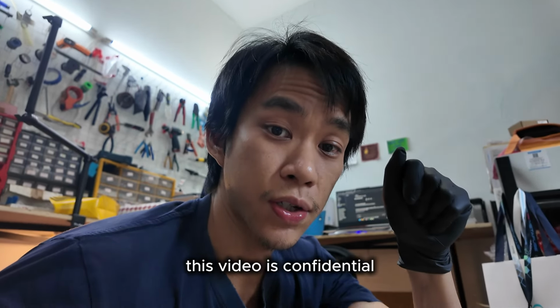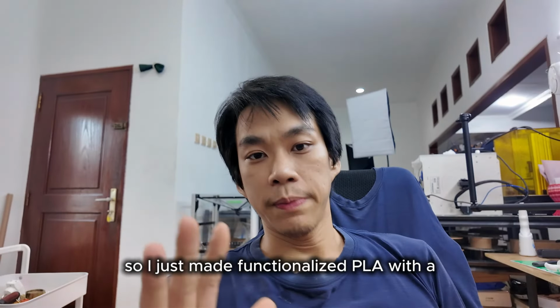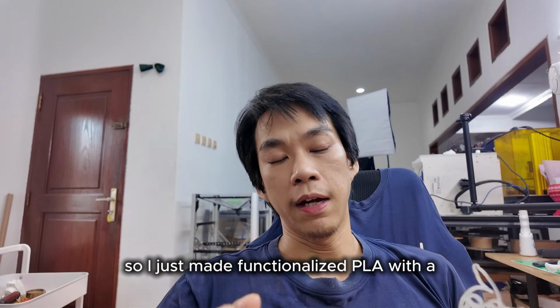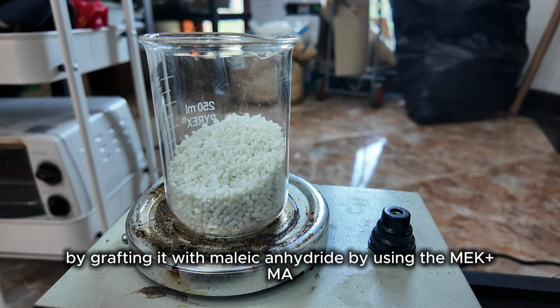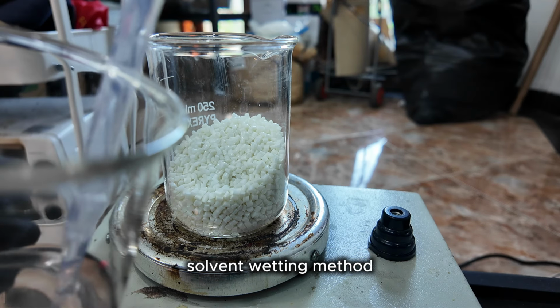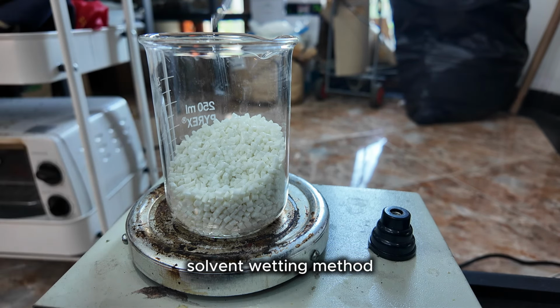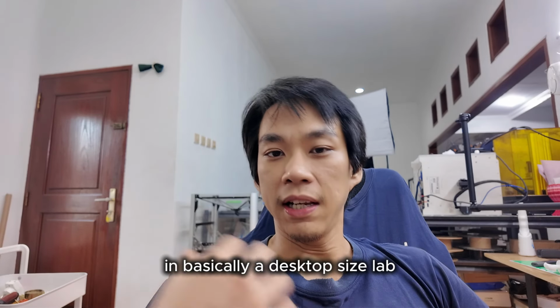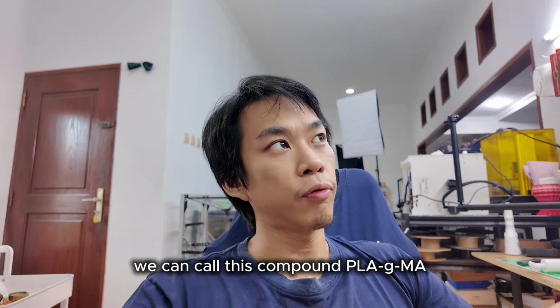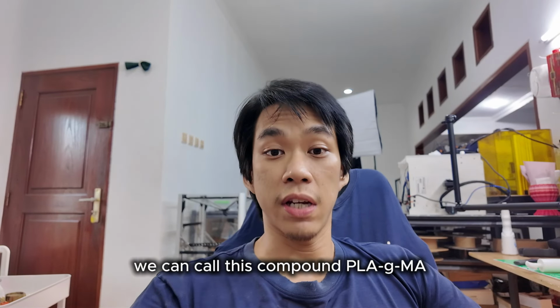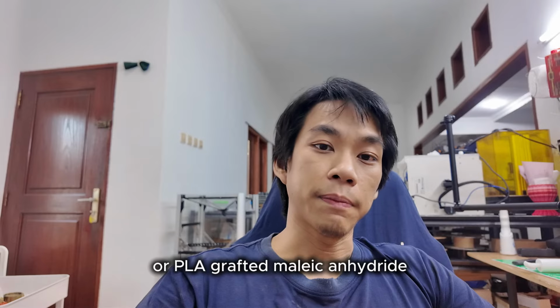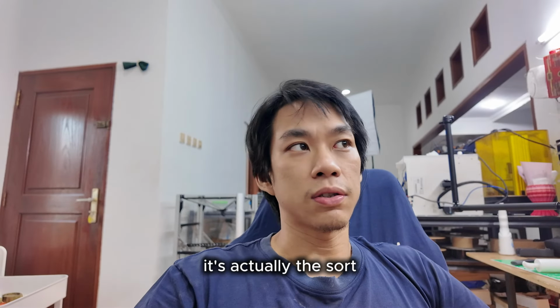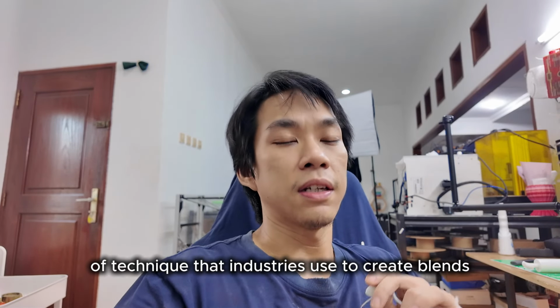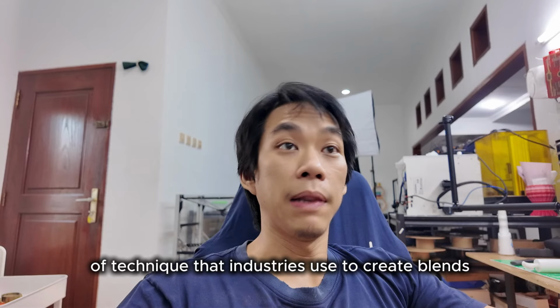I just made functionalized PLA by grafting it with maleic anhydride, using the MEK plus MA solvent wetting method in basically a desktop-sized lab. We can call this compound PLA-g-MA, or PLA grafted maleic anhydride. It's actually the sort of technique that industries use to create blends.